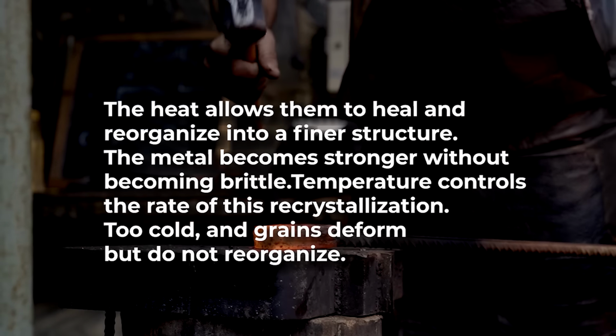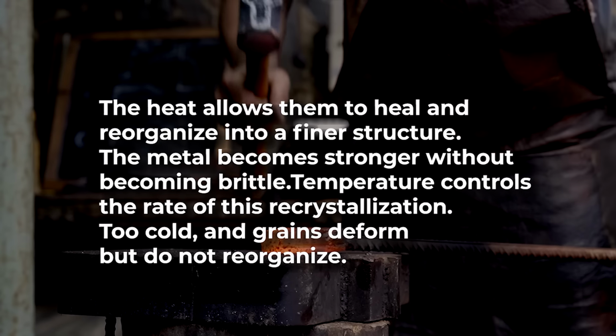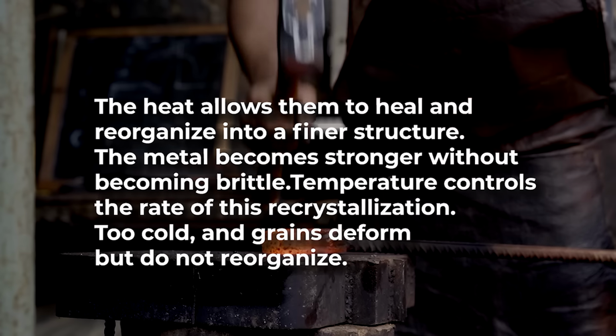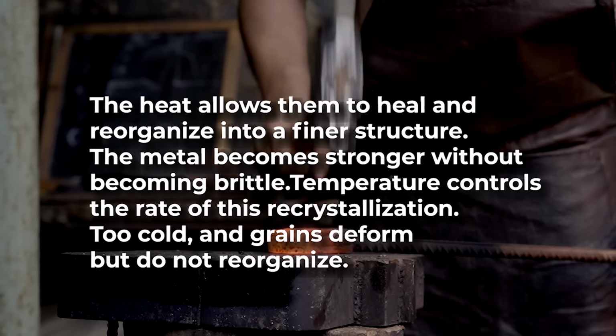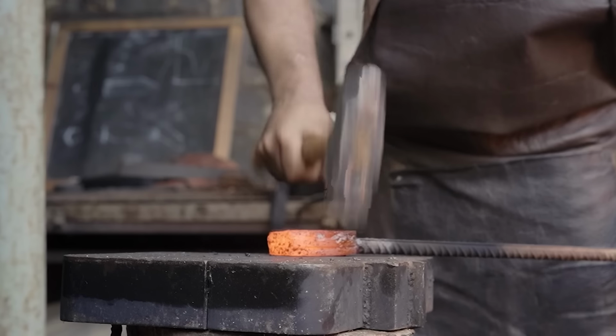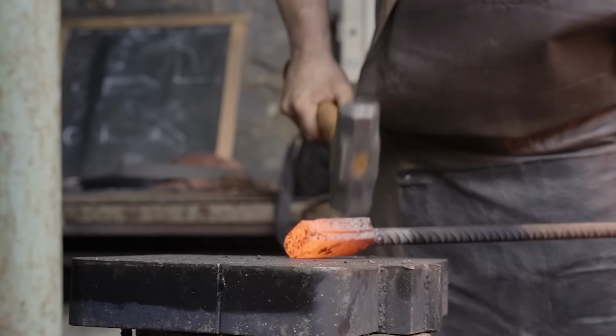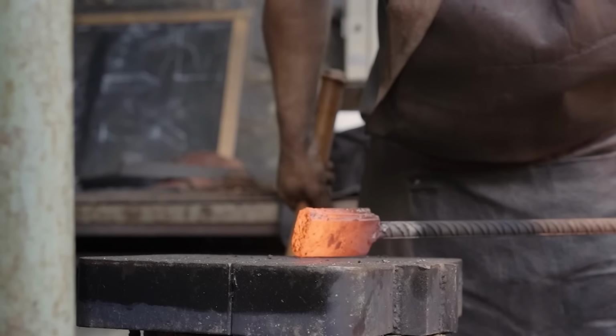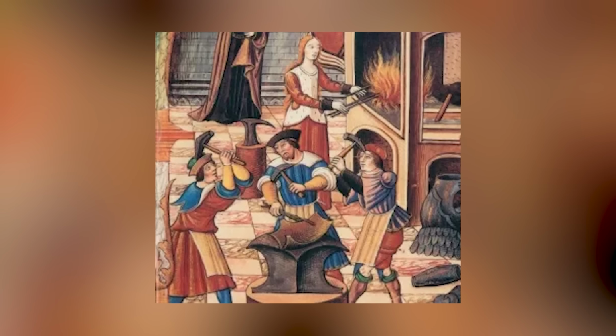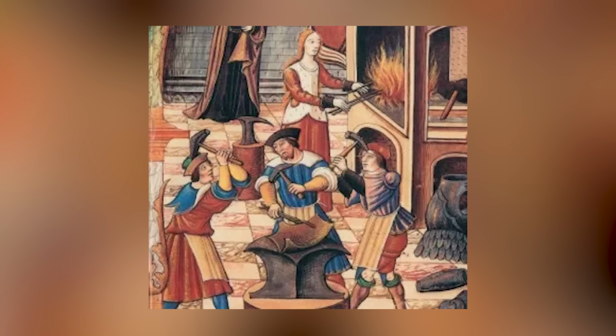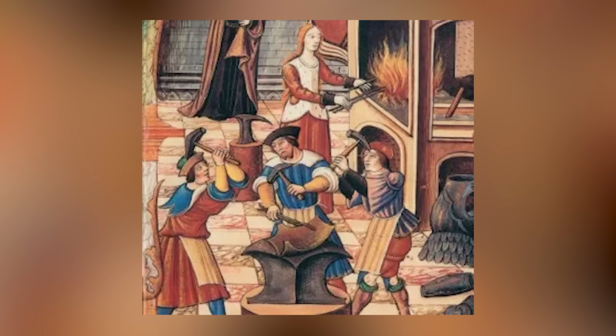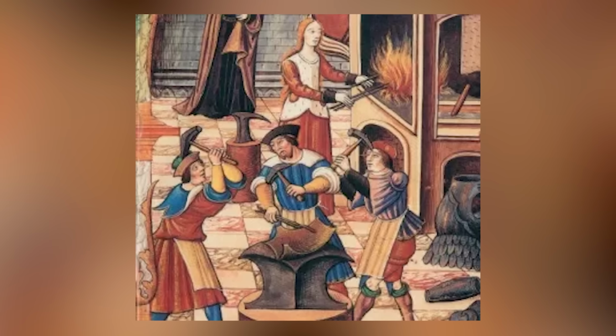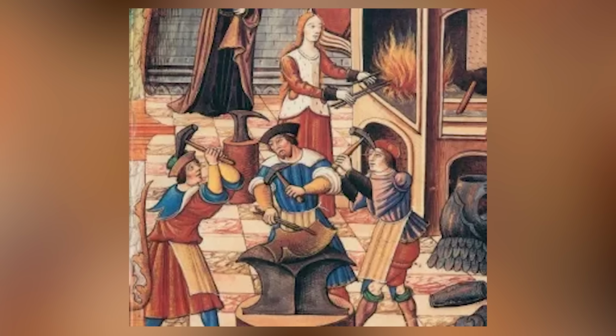Temperature controls the rate of this recrystallization. Too cold, and grains deform but do not reorganize, the damage is permanent. Too hot, and grains grow too large, losing the refinement you worked so hard to achieve. Medieval blacksmiths found the perfect zone, 900 to 1100 degrees Celsius. The temperature where each hammer strike both damages and heals simultaneously.